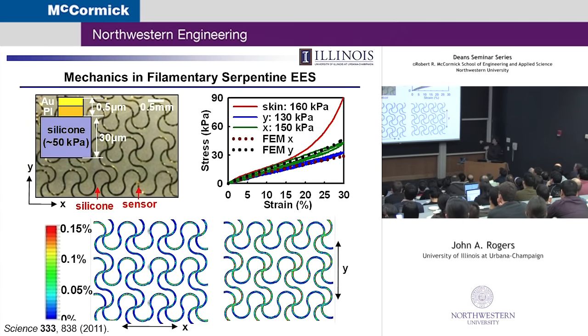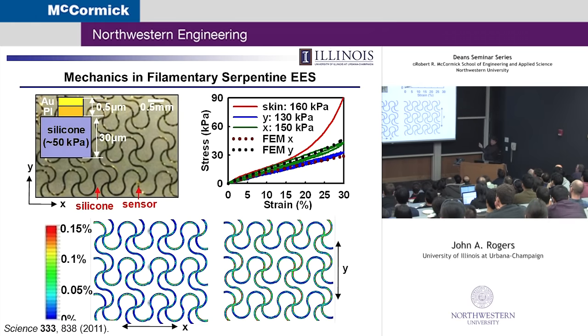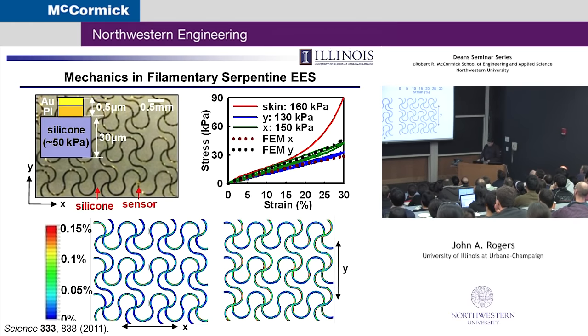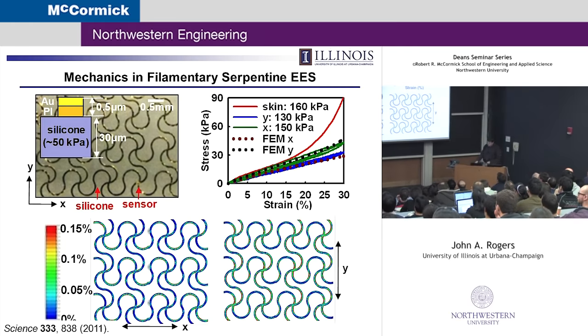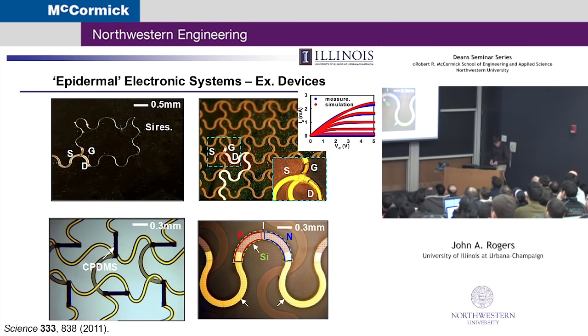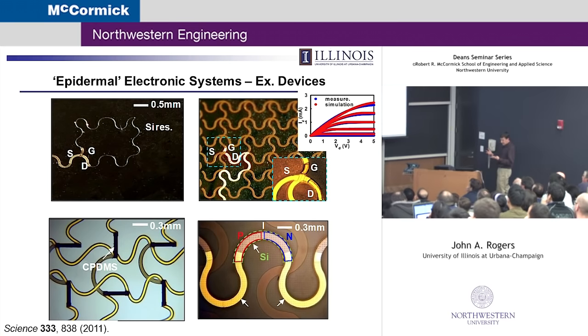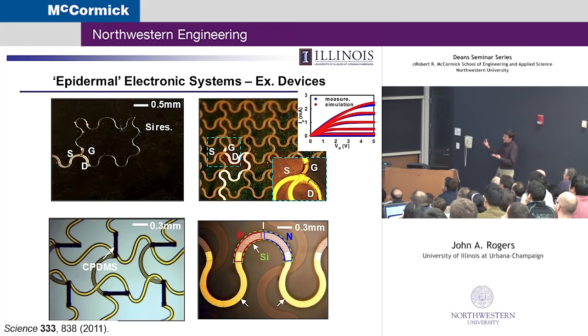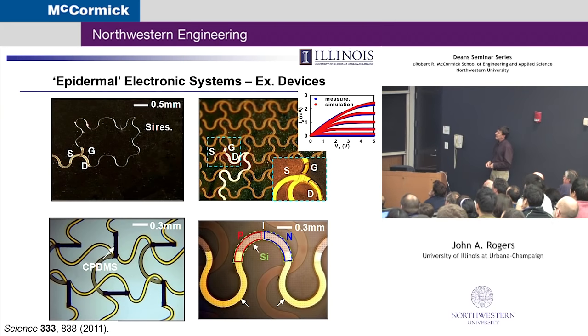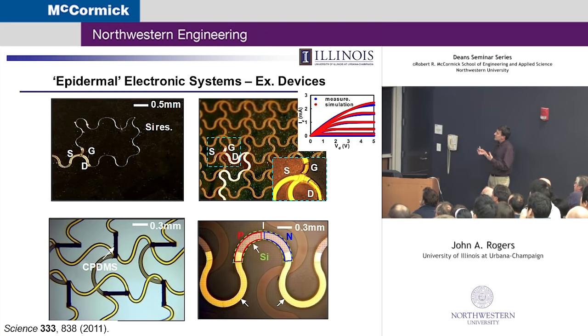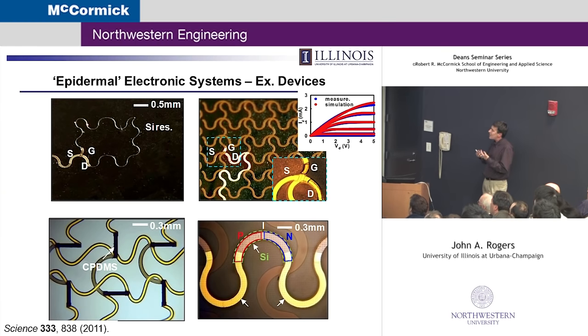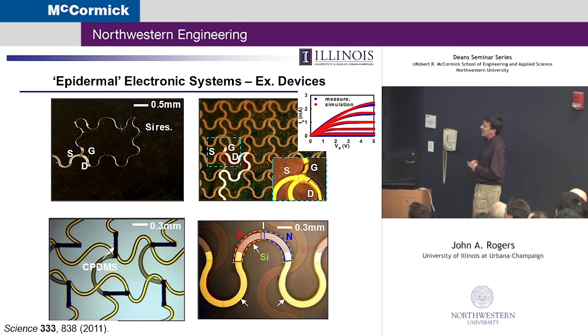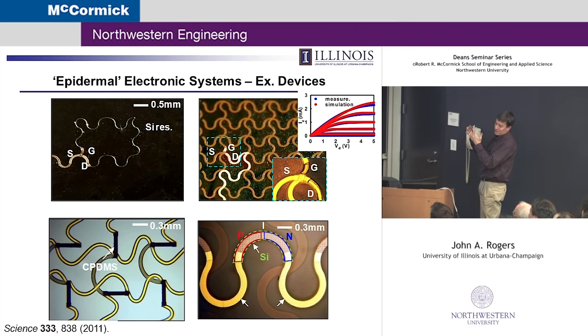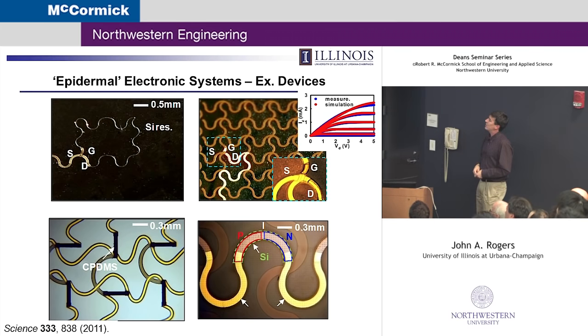Of course, these things are buckling out of the plane. They're also rotating in the plane. So there's a complex 3D distribution of displacements that's being managed in this way. But the beauty of that is it's really a foundational architecture that can accommodate all different types of devices. You can put silicon in there, gallium arsenide, gallium nitride, in some ways somewhat agnostic to the detailed mechanical modulus of the materials because you're really relying on bending mechanics, not direct tensile strain.